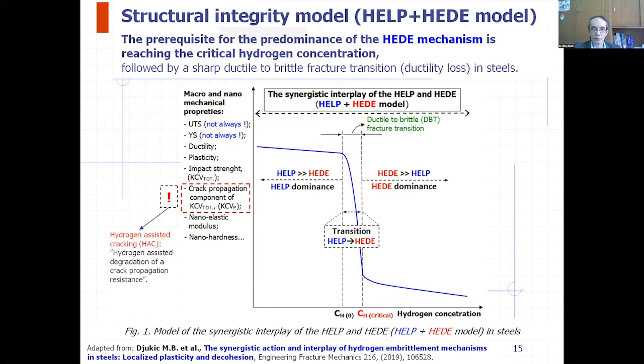Most of the research on the mechanisms of hydrogen damage and embrittlement was based on the previous uniform enrichment of metallic materials with hydrogen throughout the whole volume of the samples. Contrarily, during operation, metallic materials of industrial components are usually very unevenly saturated with hydrogen due to local corrosion processes. So the prerequisite for the predominance and activation of the HEDE mechanism, which leads to the hydrogen-assisted degradation of crack propagation resistance, which is the most important thing for the practical preventive maintenance aspects, is reaching of the critical hydrogen concentration. Upon the reaching of critical hydrogen concentration, we have a sharp transition from the HELP dominance at the